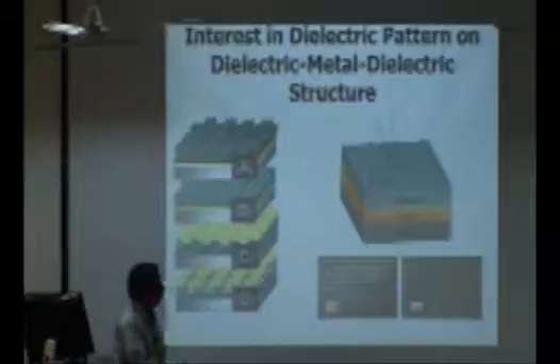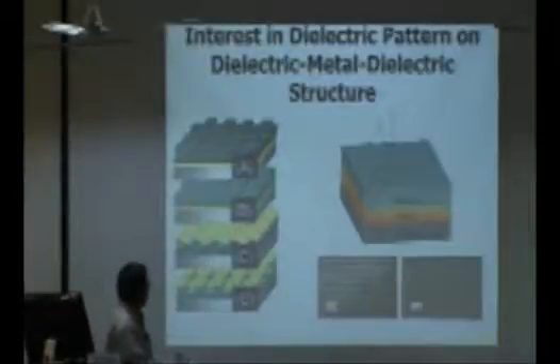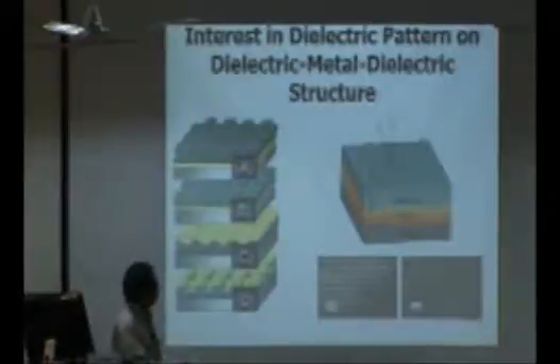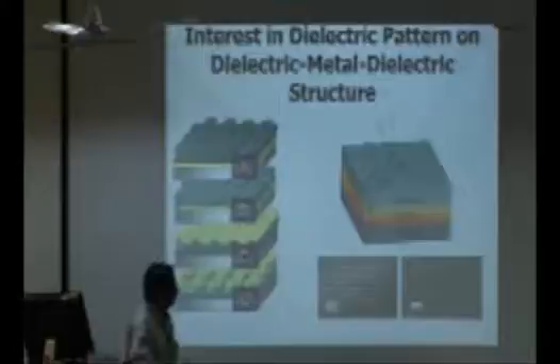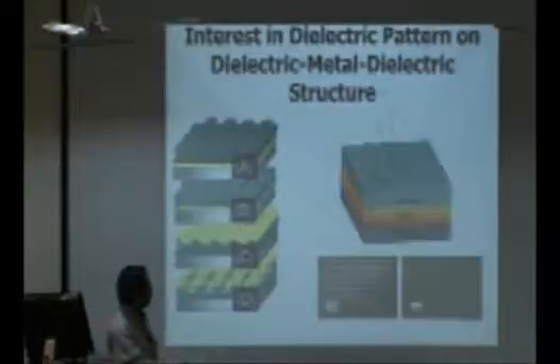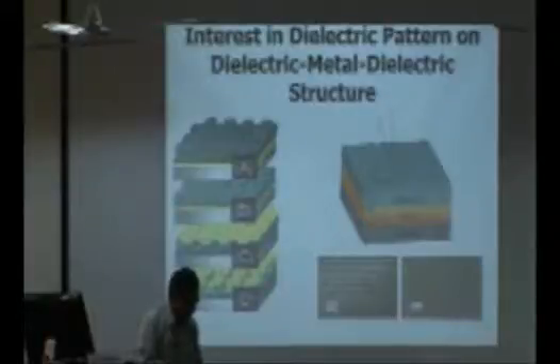Now our question was, is there any way we can overcome this angle dependence in the case of gratings, periodic structures? What we showed is that indeed it's possible if we have 2D structures like this. You can have many different variations of this, but the results will be unique. What we have chosen is an unpatterned gold dielectric interface with a dielectric pattern on top, because this is least studied in the literature.